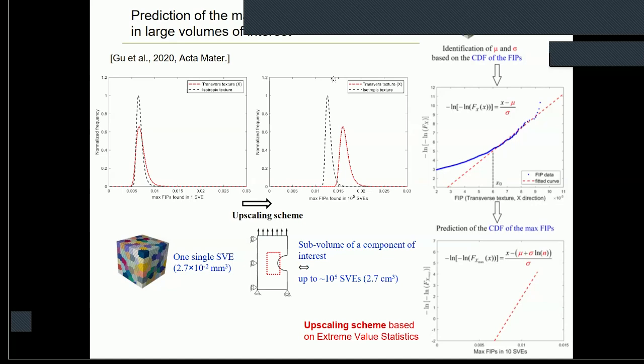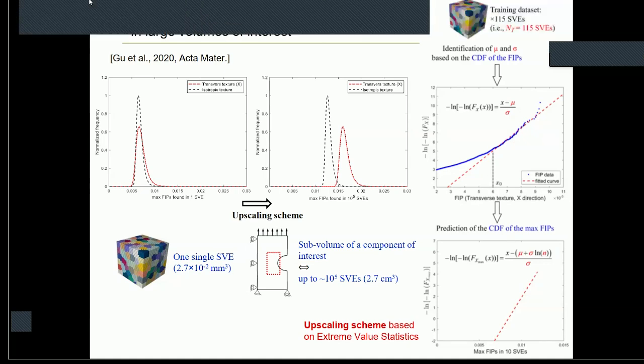So we use the so-called statistical method, extreme value statistics, to collect the statistical information of a rather smaller volume. Around 100 SVEs, we just collect statistical information from these simulations, and then we use a statistical method to predict the maximum value of the FIPs, accounting for the number of the grains. So this is a mathematical way.